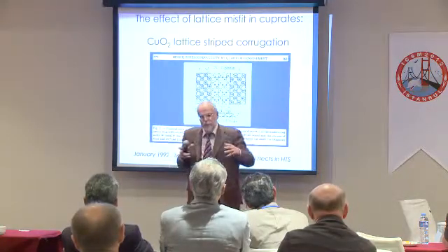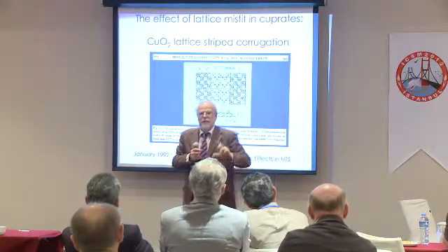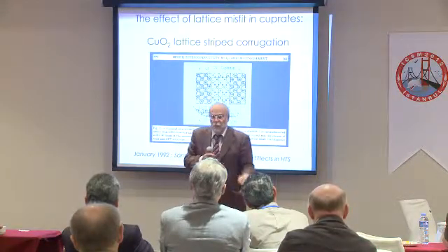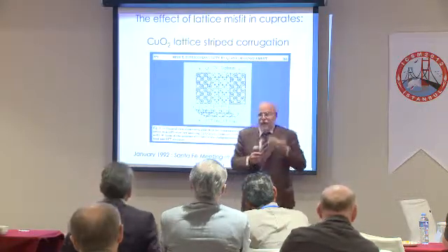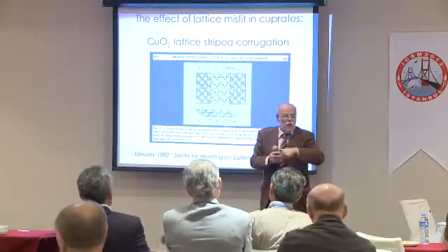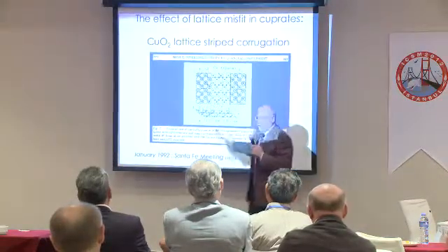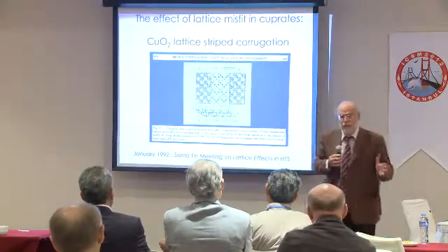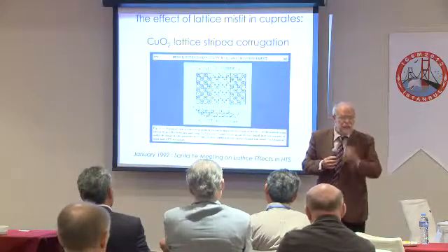When they have this compression, the system makes a homogeneous compression, or you have again phase separation. You have again the formation of modules. And that's kind of the idea of Alex, that actually when you have a polaronic interaction in a differently strained material, you can have a module of distorted lattice and a module of undistorted lattice. And this was our discovery in 92 of the stripes scenario. The real original first stripes scenario is a scenario not of spin and charge, but of distorted and undistorted lattice.